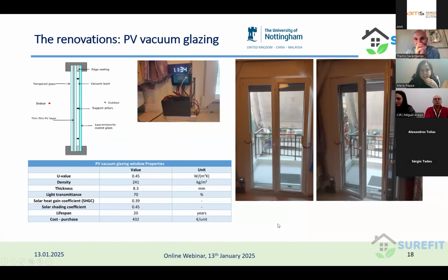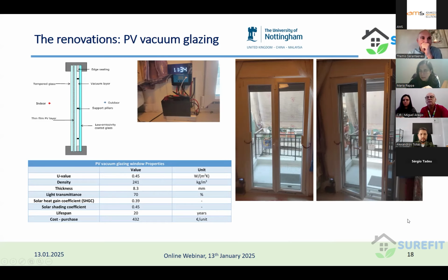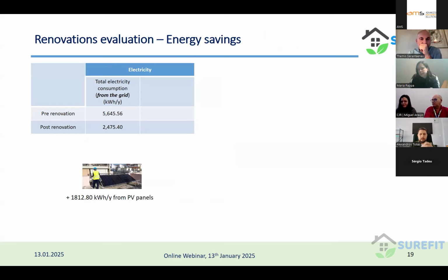And the last technology in this building was the PV vacuum glazing from the University of Nottingham. You will see more details about all these technologies after my presentation, but to have an idea, this is the system that you can see in this scheme. It consists of 2 glasses, and in between them there is a thin film of a PV layer. Then we have an air gap, and a vacuum layer, and then we have the low emissivity coated glass. And you can see the U value of this system, 0.45. The thickness, 8.3 millimeters, and the light transmittance is 70%. So we install, as you can see, this system in a double balcony door in the south facade of the building.